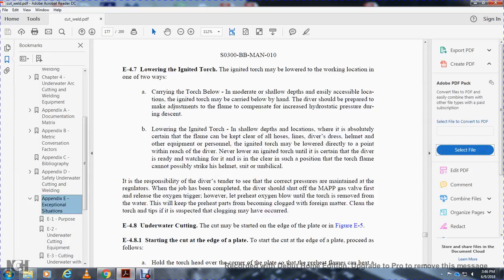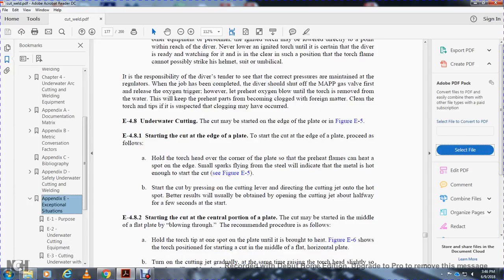It is the responsibility of the diver to maintain the correct pressure with the regulators for the job that has been completed. The diver should shut off the MAPP gas valve first, then release the oxygen trigger. However, let the preheat oxygen blow until the torch is removed from the water. This will keep the preheat ports from being clogged with foreign material. Clean the torch tips if clogging is suspected to have occurred.